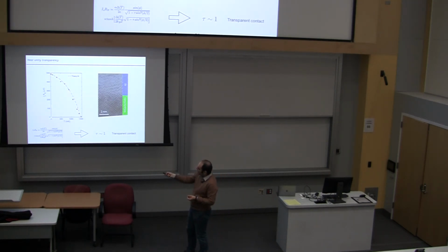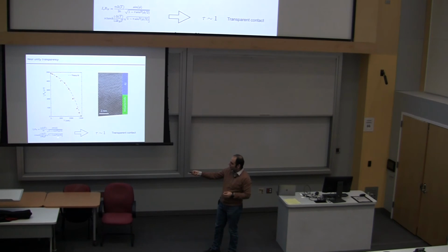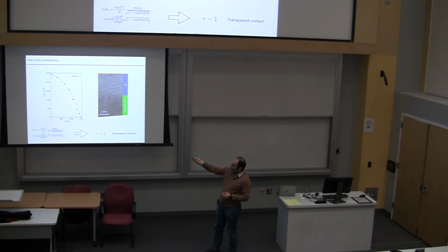So you can do ICRN as a function of temperature, right? You get a relationship, and you can sort of fit formulas to this. And if you believe me that this is the right formula for a ballistic short junction, tau in here is the transparency. I didn't try to fit this formula to that. I'm just plotting tau equal to 1 in dashed line, right? So it looks pretty good.